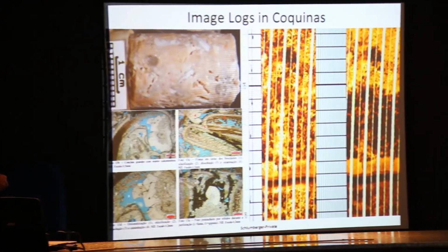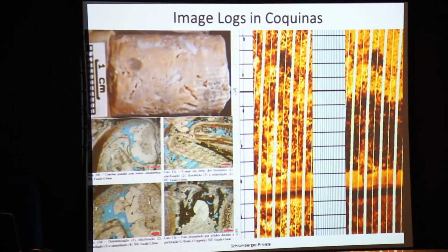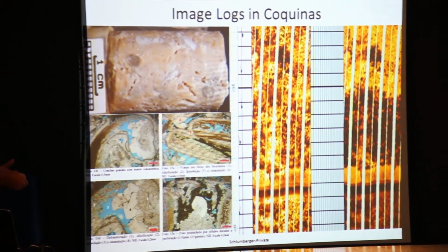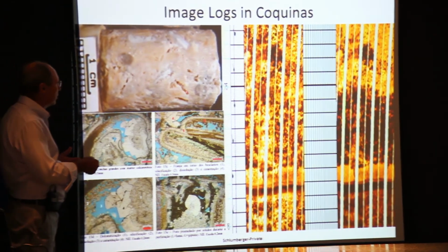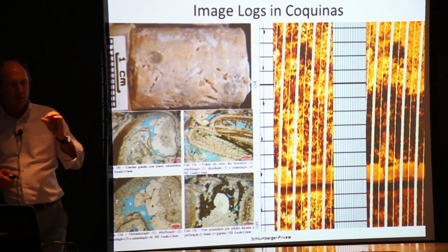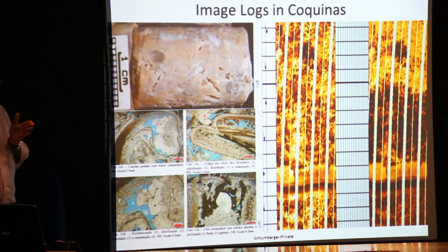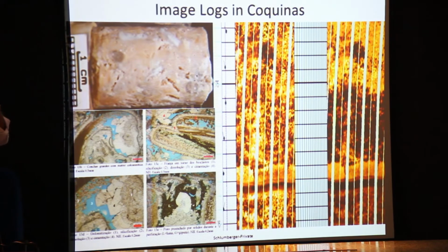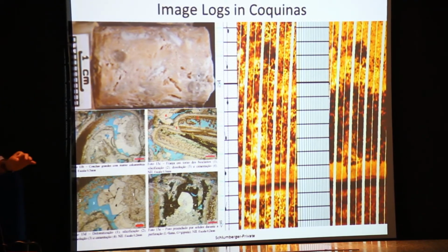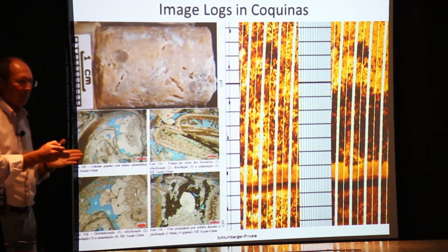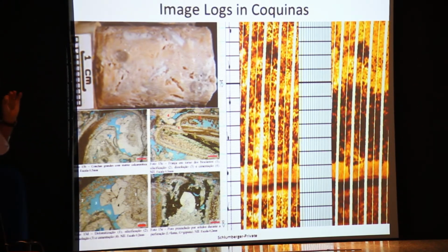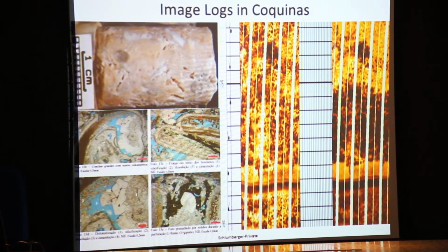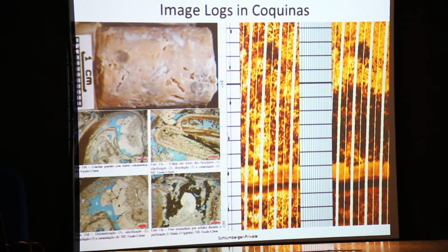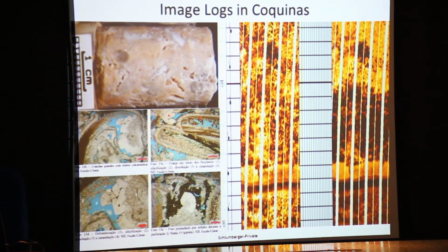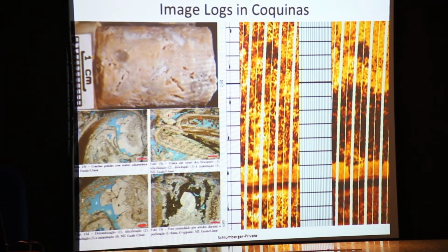And what you'll typically see on the image logs is these will exaggerate the effect of the vugs. These vugs look very big, but often when you actually look at the cores, they're quite a bit smaller. And the reason is the current from the sensors are 5 millimeters in diameter. The current basically sinks in to these small vugs, and they appear magnified on the image log. So the image log shows you where the vugs are. It's not so good in terms of quantifying the porosity of the vugs based on the image, but very good to show you where they are.